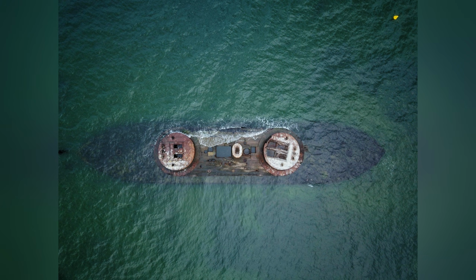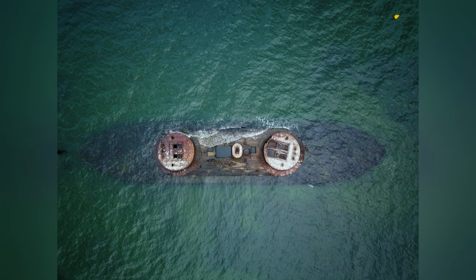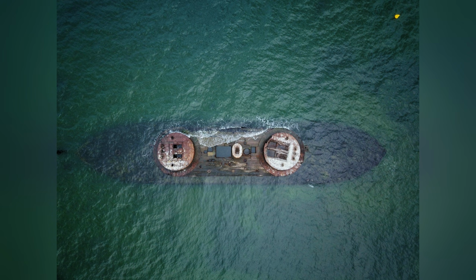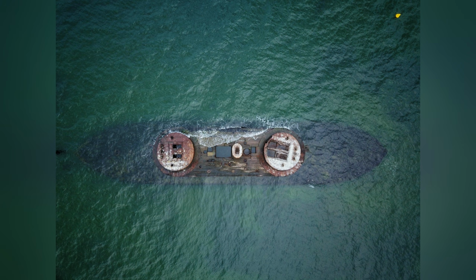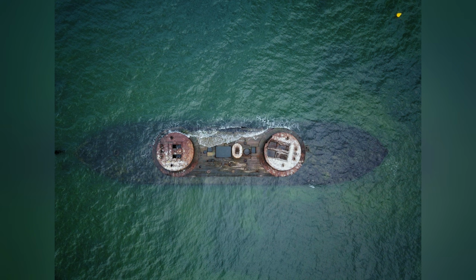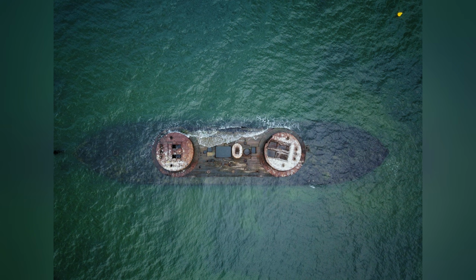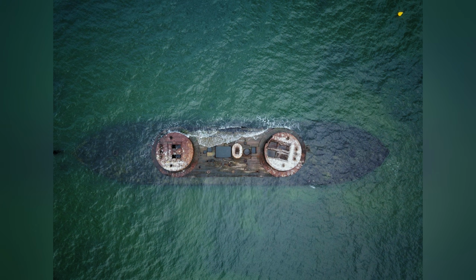The root of the structural crisis is electrochemical corrosion. Seawater acts as an electrolyte, and the iron breaks down cell by cell. The disparity in the decay rate is severe. The thick upper armor is exposed primarily to the air and occasional salt spray. It does not sit in continuous immersion, and so its corrosion rate is generally slower, though the splash and tidal zones can still be punishing.